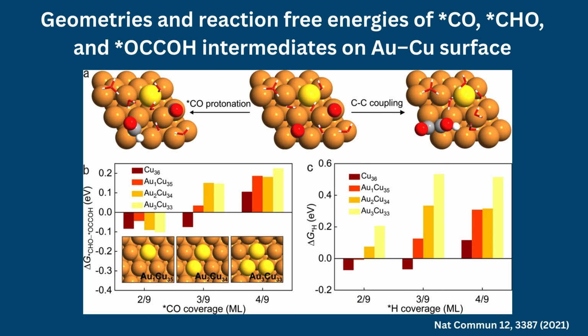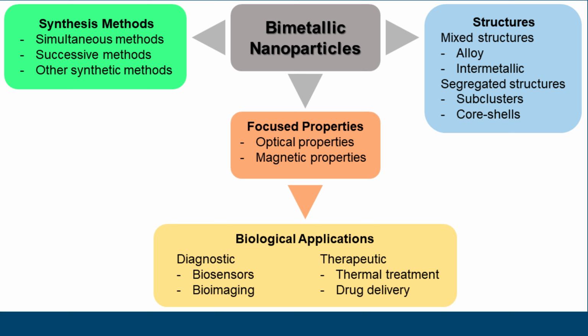Heterostructured gold-copper, Au-Cu, MMNPs exhibit remarkable selectivity for electrochemical CO2 reduction toward multi-carbon products. In these systems, CO generated on gold domains spills over onto copper surfaces, where further reduction produces hydrocarbons and alcohols.